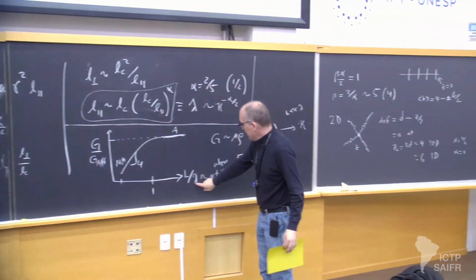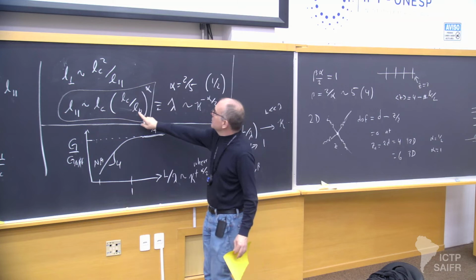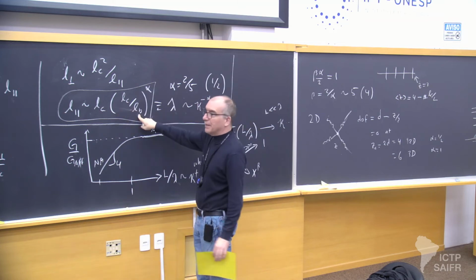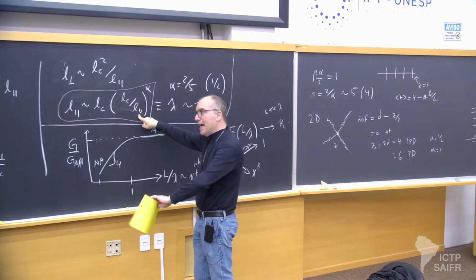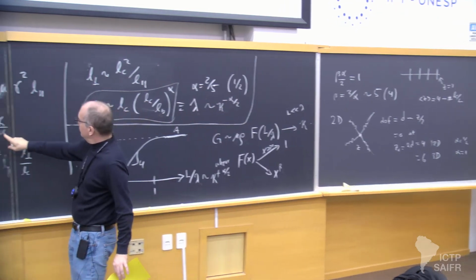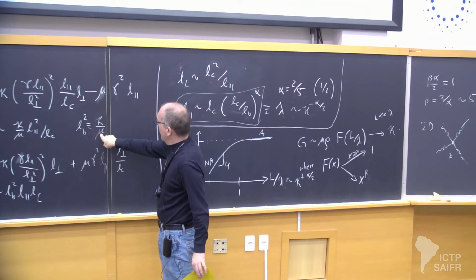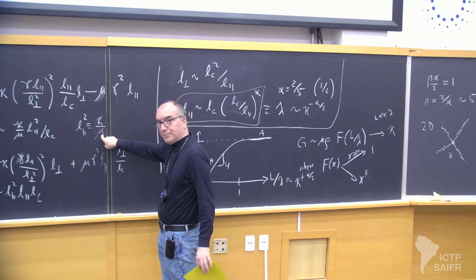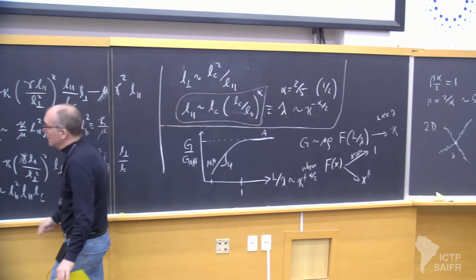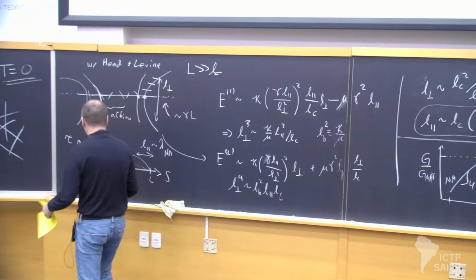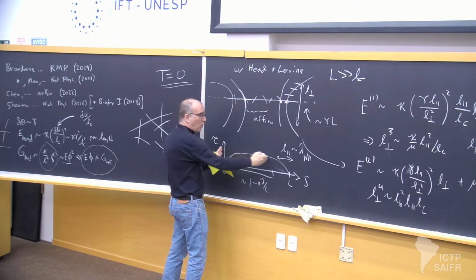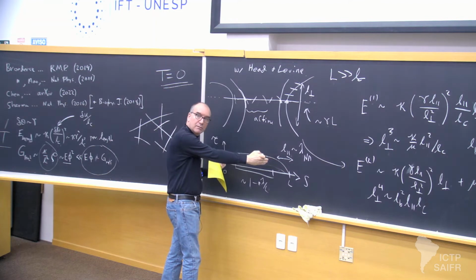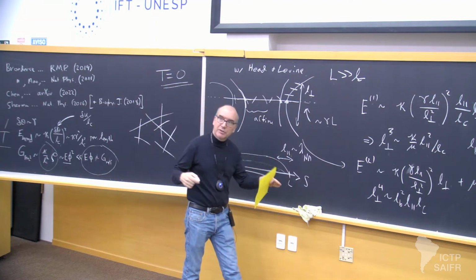Because this lambda here depends inversely on LB. So that means it goes down as I soften mu. So if I add thermal fluctuations back into the mix, I'll still get this picture. I'll just get more of the stretch region, okay? Because of a softer stretch response.